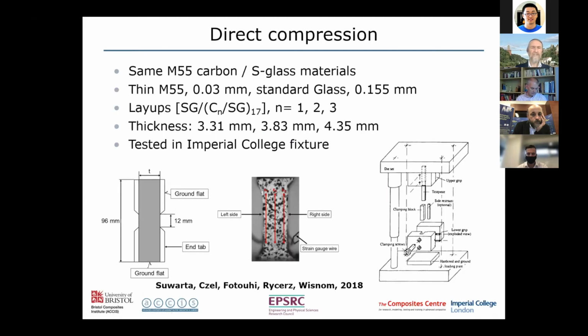So to look at this, we did tests in direct compression using the same M55 carbon and S-glass materials. But in this case here, we've got a layup where we've interspersed the carbon between the glass all the way through the thickness of the specimen. And we've varied the number of carbon plies here to have either single, double, or triple carbon of thin 0.03 millimeter ply between the S-glass plies. And then we've tested them in the Imperial College rig and looked at how they behave, measuring the strain with both a strain gauge and an extensometer.